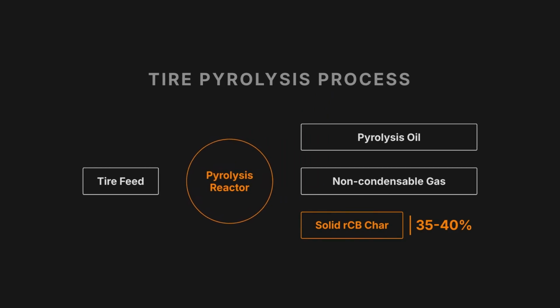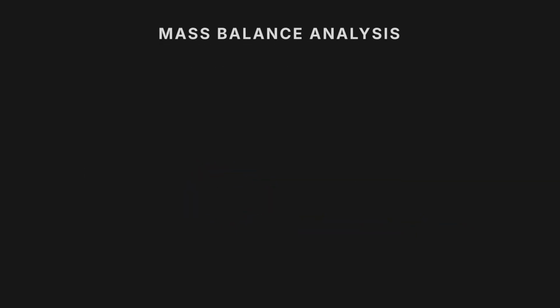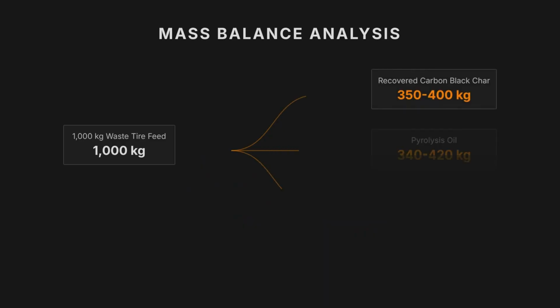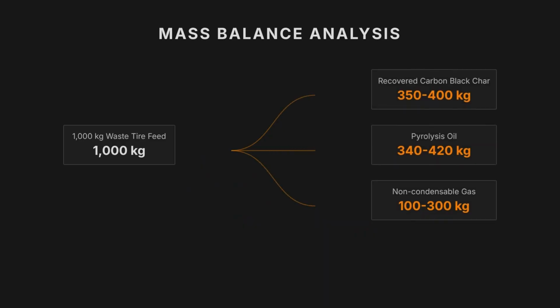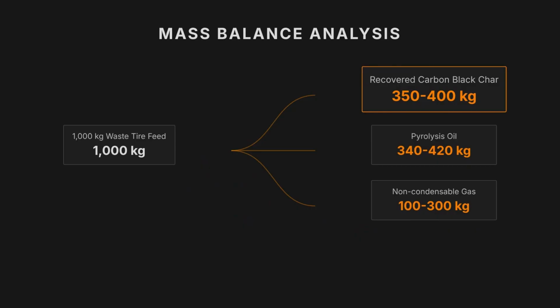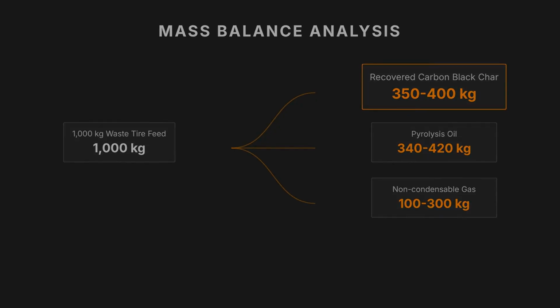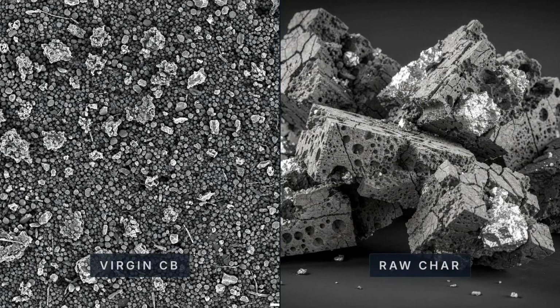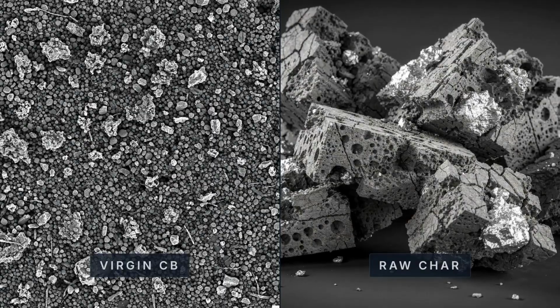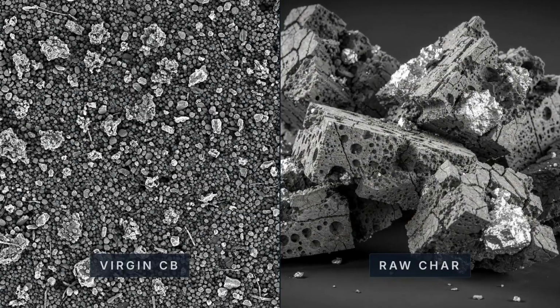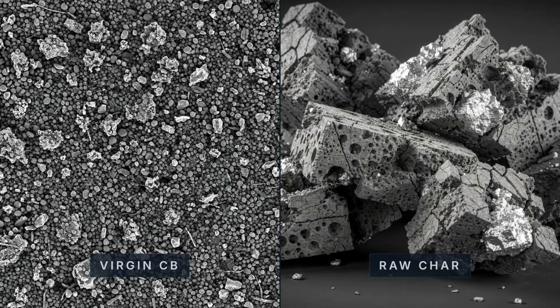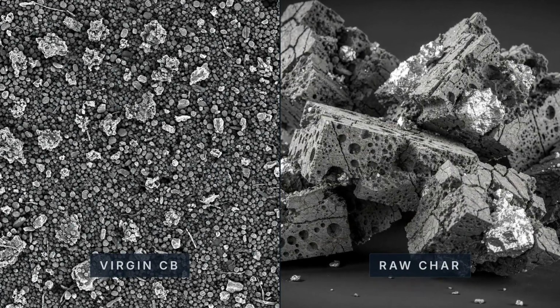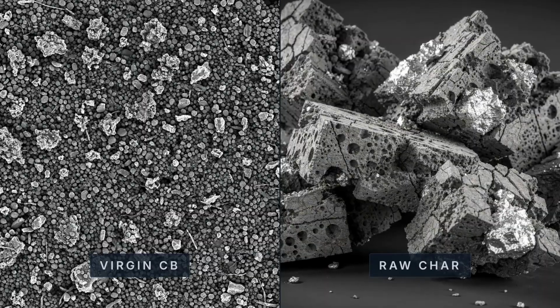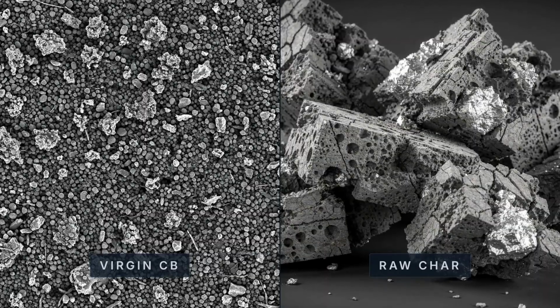Tyre pyrolysis commonly produces around 35 to 40% solid RCB fraction. For a simplified mass balance, from 1,000 kilograms of processed waste tyre, a plant may produce approximately 350 to 400 kilograms of recovered carbon black char, along with oil and fuel gas that can power the reactor itself, improving energy efficiency. Raw tyre pyrolysis char is a complex material. It contains recovered carbon black, but also inorganic ash like zinc and silica, residual hydrocarbons, and coke. A major difference is ash content. Conventional carbon black has ash below 0.5%, while raw RCB can contain 10 to 20% ash.